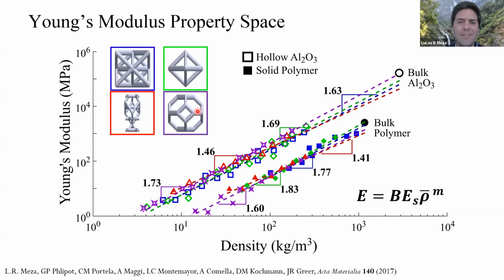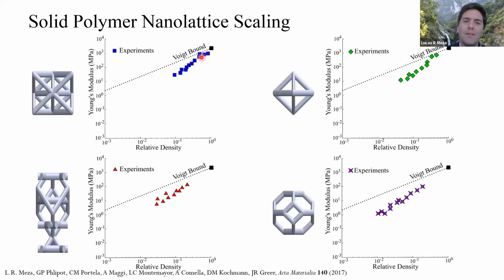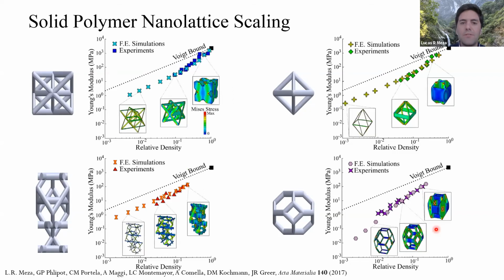So we dug into it a bit more. And so here, these are our experimental parameters, or experimental values. We did corresponding numerical simulations to match those. And we found that basically in the relative density range that we were exploring,